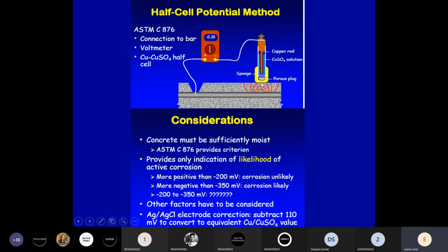reinforcement and the concrete in this particular region, there is an ASTM C876 standard which gives you the likelihood of corrosion. Again, this test is not conclusive, it is only indicative. If your value is more positive than minus 200 millivolt, it indicates corrosion is unlikely to take place. If it is more negative than minus 350 millivolt, there is a possibility of corrosion. If the value is between minus 200 and minus 350 millivolt, we are not sure.